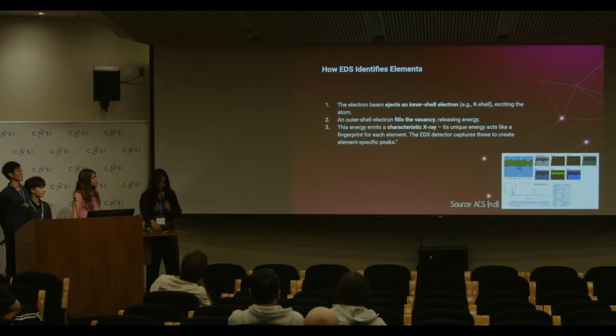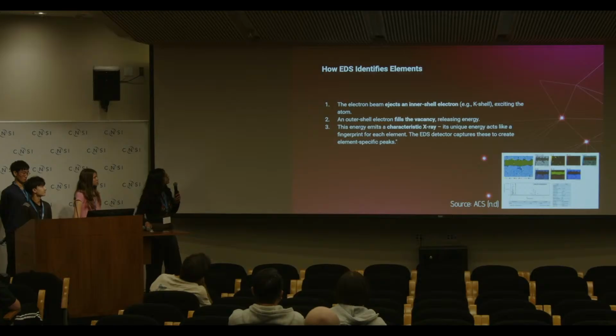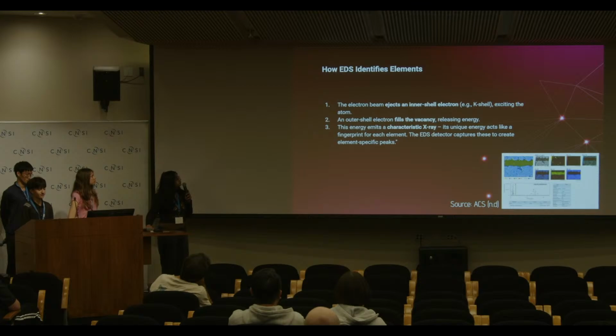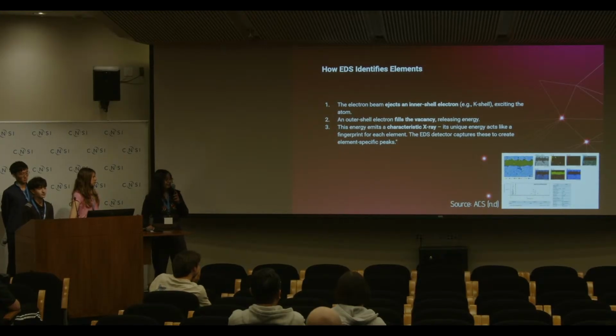Here's how EDS works at the atomic level. The electron beam ejects an inner shell electron, for example, the K shell, exciting the atom, and then an outer shell electron fills the vacancy, releasing the energy. This is the energy that emits a characteristic X-ray, and its unique energy acts as a fingerprint for each of these elements.